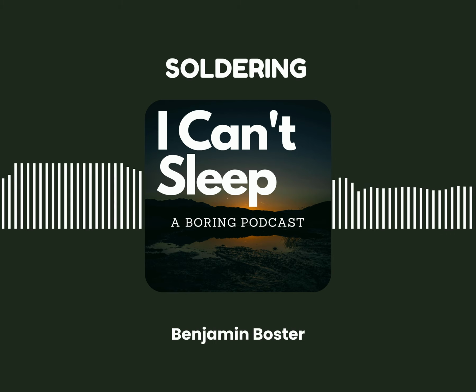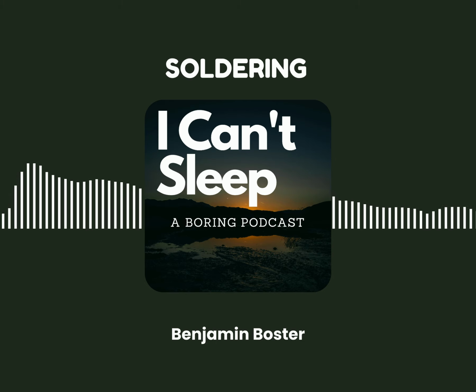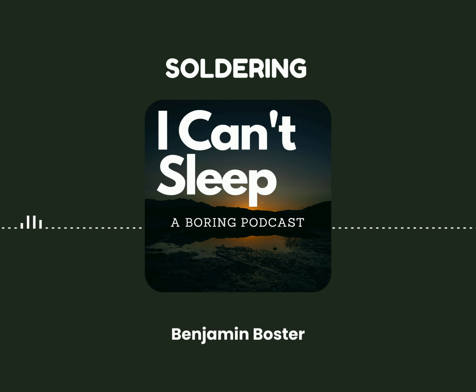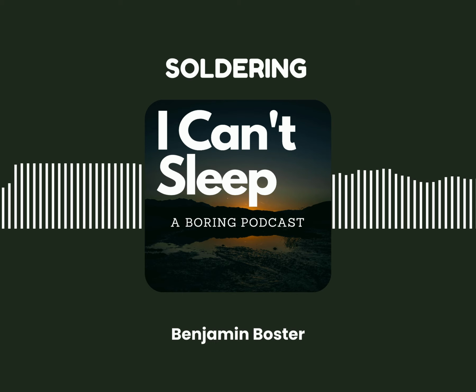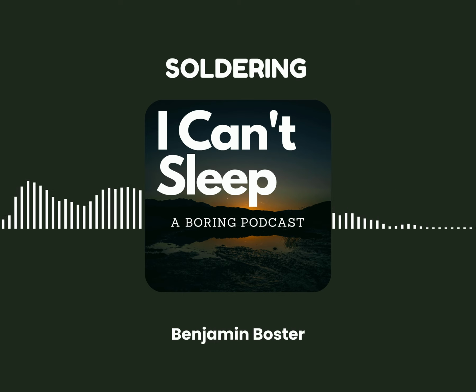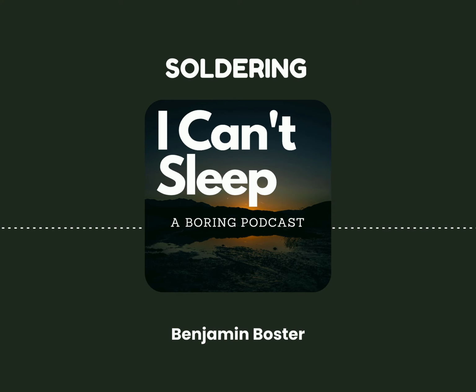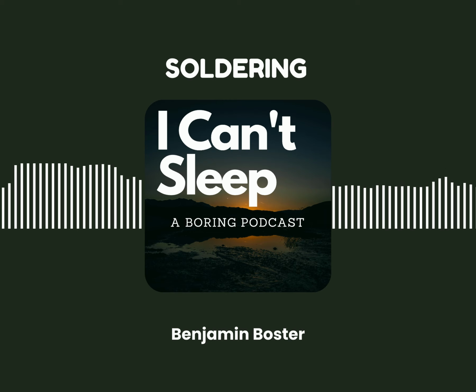Fluxless soldering, with the aid of a conventional soldering iron, ultrasonic soldering iron, or specialized solder pot, uses an active solder that contains an active element, most often titanium, zirconium, or chromium. These active elements, owing to mechanical activation, react with the surface of materials generally considered difficult to solder without pre-metallization. Active solders can be protected against excessive oxidation of their active element by addition of rare earth metals with higher affinity to oxygen.